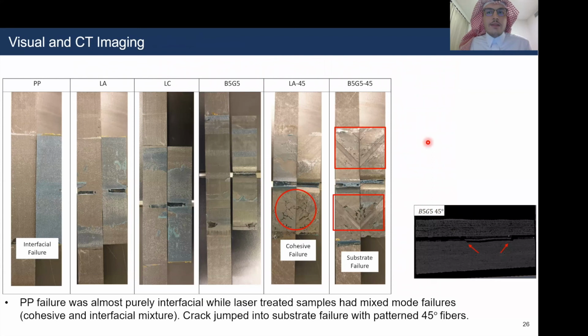So to analyze the failure mechanisms that happened, visual and CT imaging has been taken, and it was noticed that for the PP pretreatment, an interfacial failure happened, such that the crack propagated at the interface between the adhesive and the substrate, or the adhesive and the skin in this case. For the LA, LC, B5G5, LA45, cohesive failure occurred, or a mixture between cohesive failure and interfacial failure. I explained what interfacial failure is, and cohesive failure is when the crack propagates inside the adhesive, and this results in adhesive present on both sides of the skin and the stiffener.